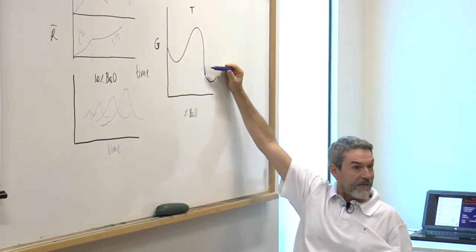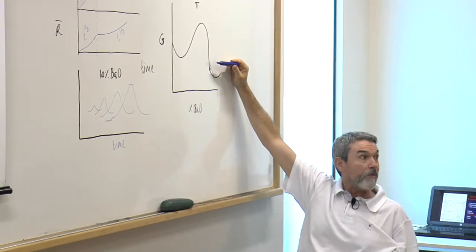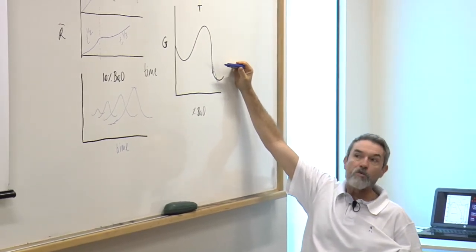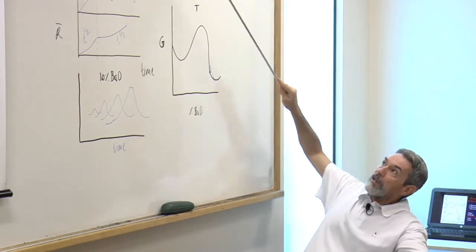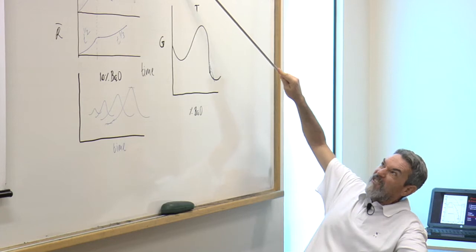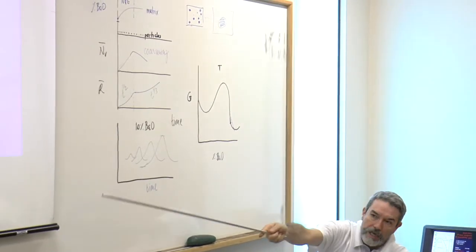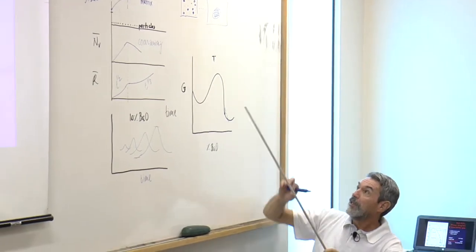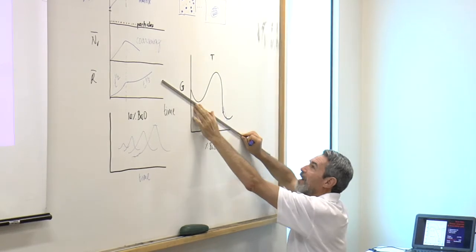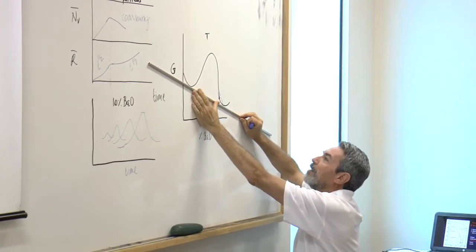But the best way to decrease the surface energy is to form a large fluctuation. That's why I told you that the chemical composition of these fluctuations here are almost pure silica. Then it's a very large fluctuation of this size here. Let's take now a large fluctuation.